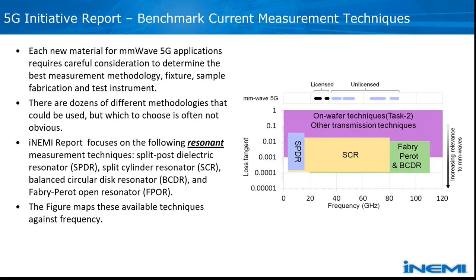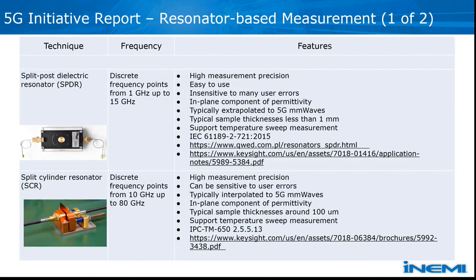What we did, if I may ask for the following slide, is evaluate features of those four methods to see what we can achieve with them, where the limitations are, and to which application they are suited. Starting with the SPDR, those test fixtures work at discrete frequency points. They are available from 1 gigahertz up to 15 gigahertz. They are easy to use and assure high measurement precision. They give us the in-plane component of the permittivity, and based on results achieved with those measurement techniques, we can extrapolate the values to the 5G millimeter waves range.